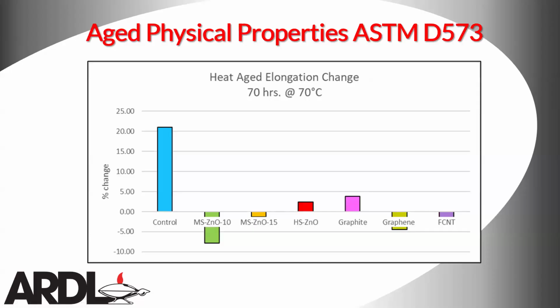So now if you look at your heat aged elongation change, here what you're seeing is your control had a positive change of like 22%. So if the elongation is going up, then that tells me my compound is softening more than likely. And you can see that you have almost a 4-time reduction in your heat aged elongation change just by adding some thermally conductive filler to replace some of the silica in your actual tire tread formulation. And here you will see that your higher levels of zinc oxide and your functionalized carbon nanotube had the least amount of change.